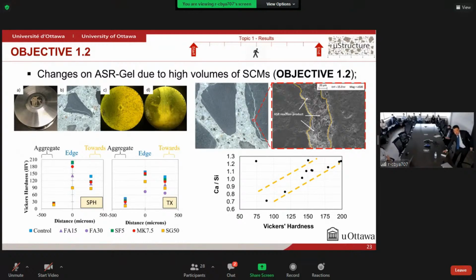So to try to explain this behavior in the cement paste, we then checked the chemical composition of the ASR gel through EDS analysis. And as we can see here, changing the ratio of calcium to silica in the ASR gel, there's almost a linear correlation with the Vickers hardness. In other words, if we use more SCMs, we will have a decrease in this ratio and then a decrease in the Vickers hardness as indicated here. And according to the literature, decreasing the amount of calcium in the ASR gel changes the swelling properties of the gel. Now, combining these results with the results on the ability to self-heal of the combination of crystalline admixtures and SCMs, we can then explain why we had such a lower value for compressive strength reduction.